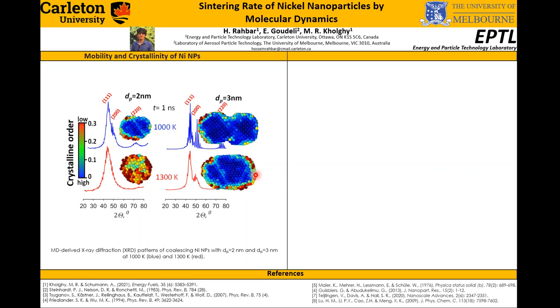It is worth mentioning that the small values of D less than 1/10 correspond to FCC crystal structure, while large value of D, typically more than 3/10, indicate a glassy or liquid nanoparticle. As the figure shows, during the sintering, surface melting starts from the outermost layers of nickel nanoparticles. So, the nanoparticle melting temperature could be highly dependent on the size of particles.